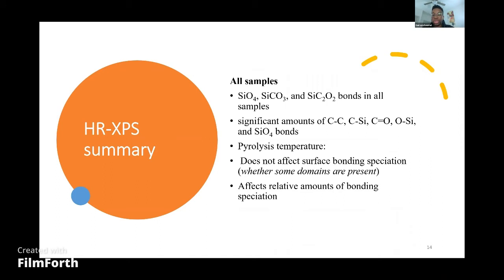Similarly, we're also able to see significant amounts of bonds corresponding to C-C, C-Si, C double bond O, and so on, which is expected. But what is also interesting to see is that with increasing pyrolysis temperature, we don't see significant changes in the bonding speciation on the surface of these materials. What do I mean by bonding speciation? Which bonds are or are not present, as well as their corresponding domains. Instead, what we do see is a change in the relative amounts of the different bonds and their respective domains.